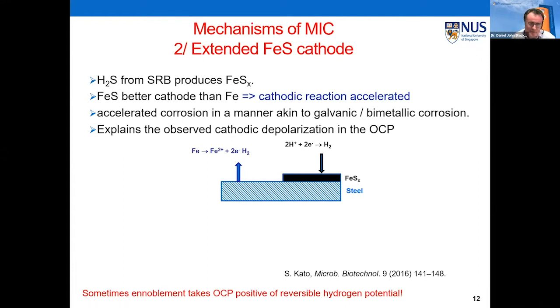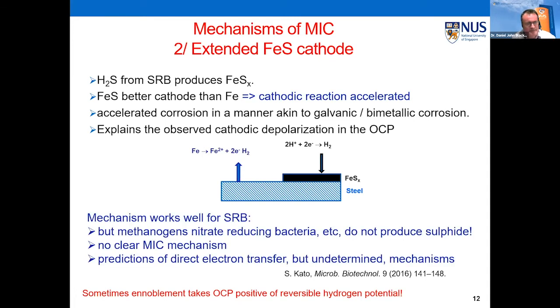Doesn't work if the ennoblement goes positive for the reversible hydrogen potential, of course. But it worked well for SRB, and I used to be happy. But then people have started finding corrosion for methanogens, nitrate-reducing bacteria. They don't produce any sulfide. And so if there's no sulfide, this mechanism doesn't work.